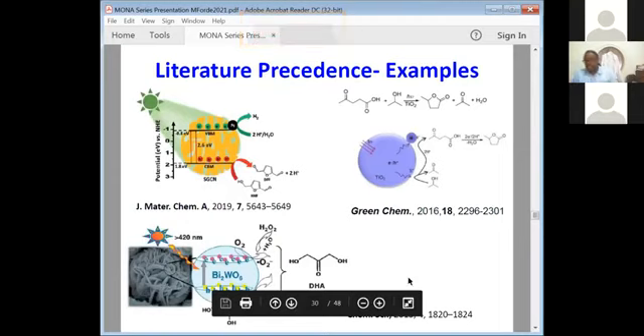In the literature, over the last few years, actually, people have published this concept where they can create hydrogen from water and at the same time do some oxidation of another molecule that was in solution. So an example over here is the hydroxymethyl furfural example. They're using isopropanol as a hydrogen donor to do levulinic acid to GVL. At the bottom, they have glycerol, and we're interested in glycerol, doing oxidation of glycerol using oxygen. So this is oxidation hydrogenation.